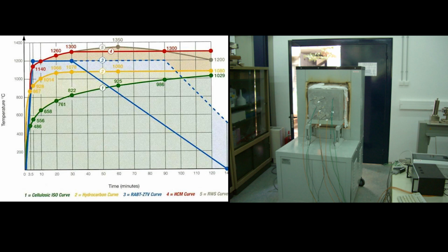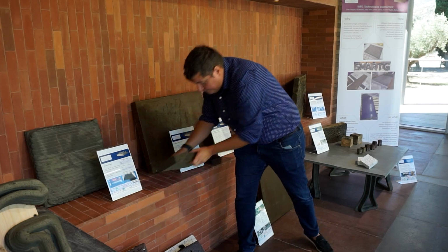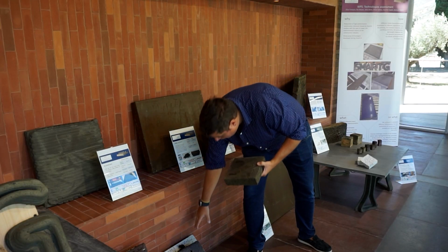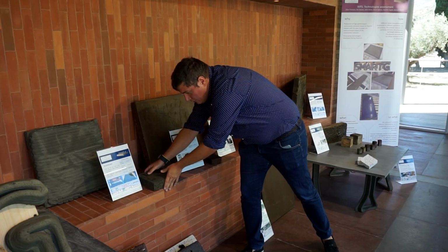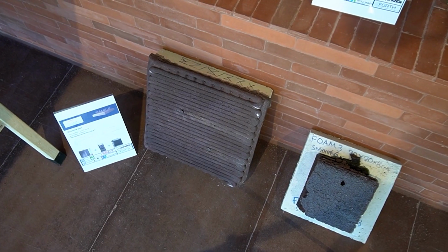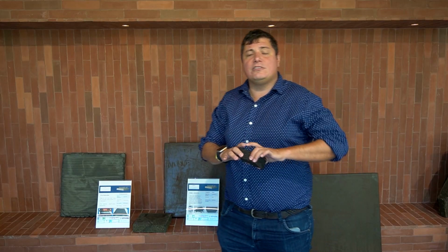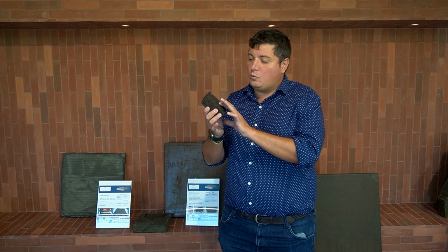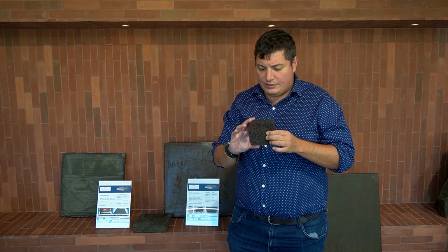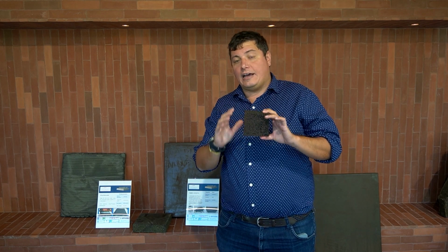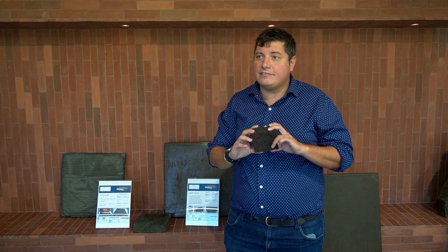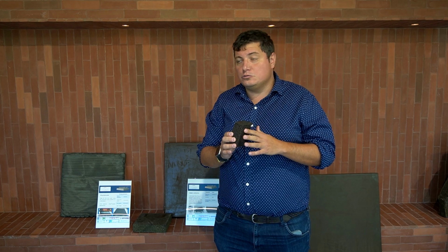During the Smartg project, we evaluated the materials we developed under fire resistance. For this reason, we evaluated under the ISO 834 time temperature curve in a custom-made furnace that can simulate all the time temperature curves. The fire resistant materials that we developed are applied on a concrete surface, as you can see here, and then they are exposed to the ISO 834. And we evaluate the temperature at different depths of the specimen, here behind and here in the middle. One of the best specimens during our evaluation, which behaved very well in terms of fire resistance and cracks after heating, was the one prepared by University of Aveiro with spheres. This behaved very well since it achieved one of the best thermal gradients, and at the same time, after the test, no cracks or yielding appeared due to loss of humidity.